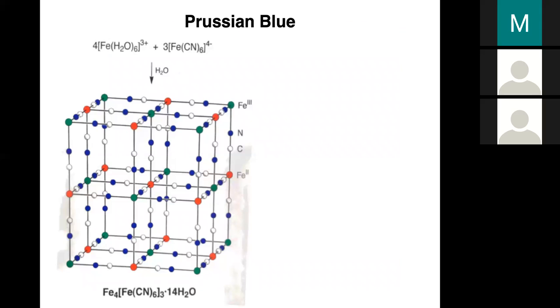Okay, so let's take a look at Prussian blue in a little more detail. The reaction that we just saw is formulated at the top. So aquated iron 3+, this is the yellow solution, we're adding it to that colorless solution that contains these octahedral FeCN6 4- anions. And what's happening is the nitrogen ends of cyanide are displacing water in the coordination sphere of iron 3+ and making these bridging linkages, where we're going from iron 2 to carbon to nitrogen to iron 3.